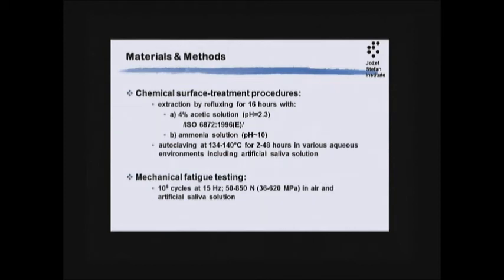And there was nothing at that time but this ISO standard for checking the chemical stability of the material by refluxing, and we used that. And afterwards, when we did mechanical fatigue testing, we went up to 1 million cycles, 15 hertz, 50 to 850 newtons, which will correspond roughly to, let's say, maximum 620 megapascal. That would be roughly about 60% of the average strength of the control group.